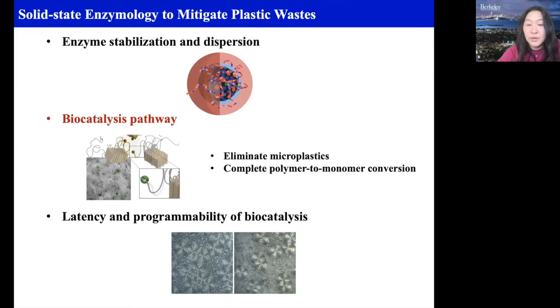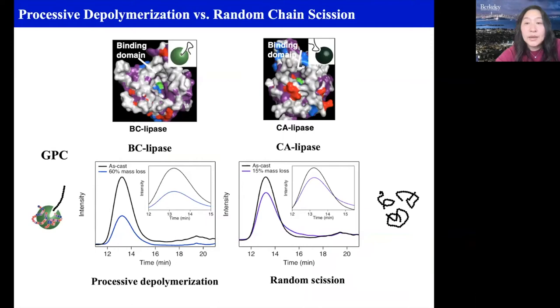So this is getting into a little bit more on the molecular level, what we can do in order to modulate the degradation pathway for the system to really go through a polymer to monomer conversion with near complete, over 90% conversion. So there are a couple of things. One is that we look at the binding pocket of the enzyme. So the active site can be either surface exposed or it can have a very deep pocket.